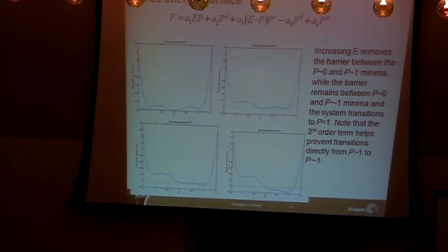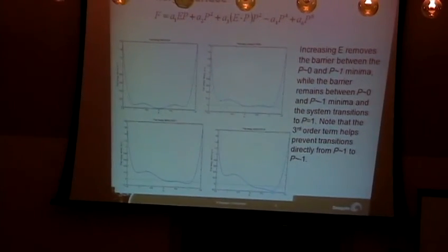You identified a specific state. What's the actual physical reality of that state? It's not clarified here. I was deliberately vague about this. It could actually be described in terms of local atomic ordering. For example, when you have irregular current channels in these devices and you increase the current density, you can have some local reordering of vacancies or defects in the system. That can be one thing, or it could be actual ferroelectric polarization. Generically, it's a state statement.